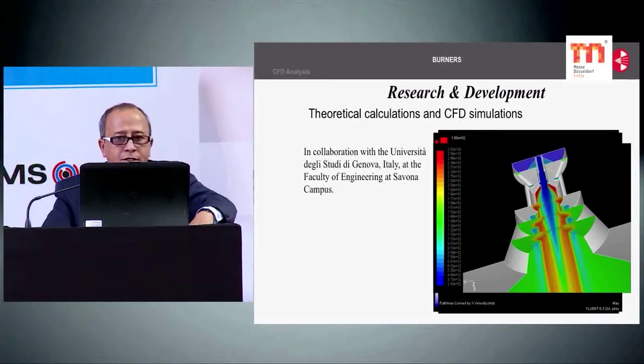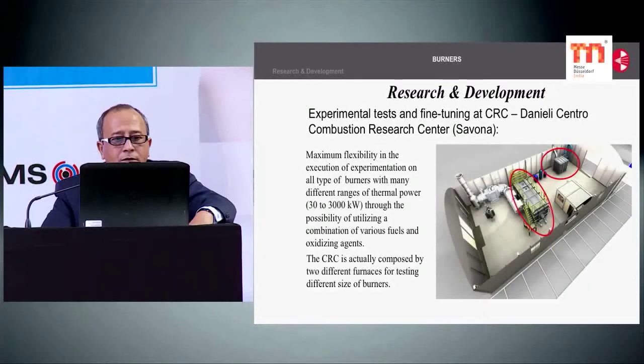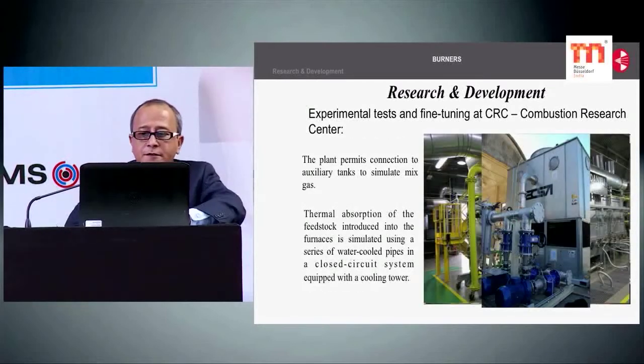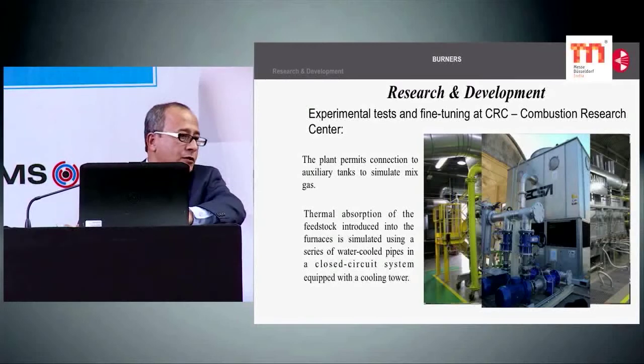Then we have also burners for heat treatment furnaces, which are long flame burners to achieve very good temperature uniformity throughout the furnace width. These are high-speed flame burners with preheated or cold air, both. This can be self-recuperative as well to have very good thermal efficiency. We can heat up with a 1250 degree, 1050 degree furnace temperature. The preheat air can be as high as 800 to 900 degrees centigrade.